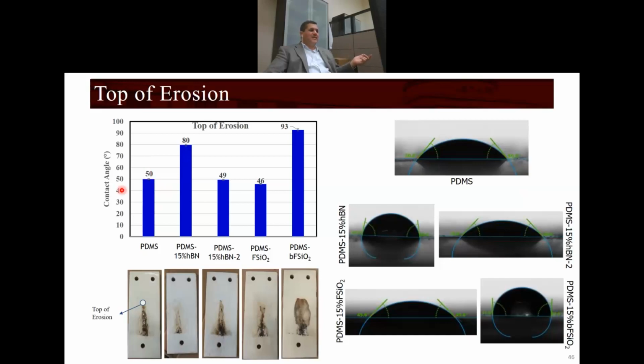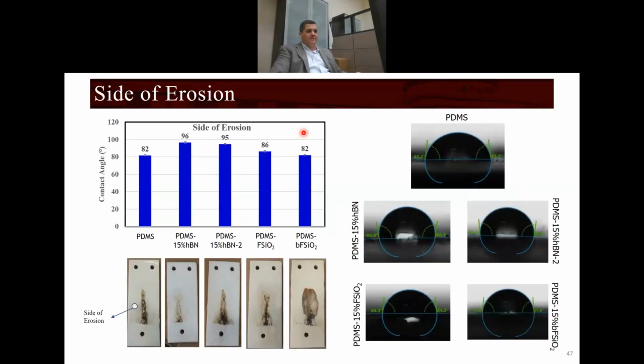This test was done in maybe not more than 4 hours until you reach 4.5 kilovolt. But it lost its hydrophobicity compared to something like fumed silica, for example. And this is a very important point to take into consideration. At the side of the erosion, also nothing much happens, because it does not get exposed to the electrical charge as much.